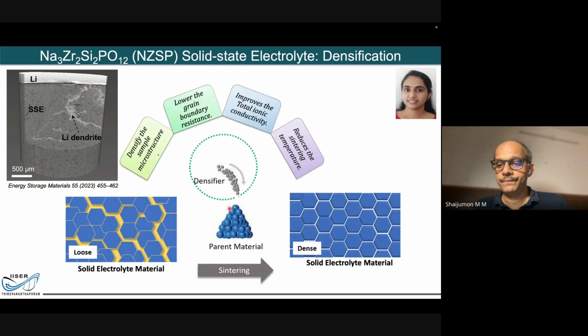So one way to mitigate this is, so this is the loosely packed solid electrolyte material. What if we densify this parent material by adding some densifiers, right? This is something that one of my PhD students, Ashwati, is working on, where she's trying to add some oxide materials into this parent material, and that oxide material goes and sits at the grain boundaries like this. And you see, schematically, in the cartoon, that it becomes much denser. And the moment it becomes denser, you get rid of this dendrite propagation, and that will essentially improve your cyclic stability. I can cycle my batteries for a much longer time or longer cycles, right?